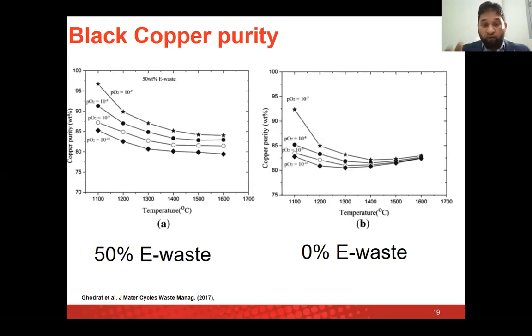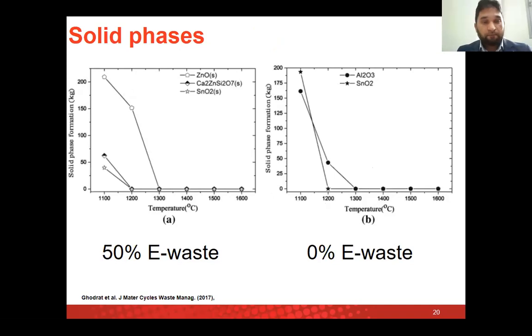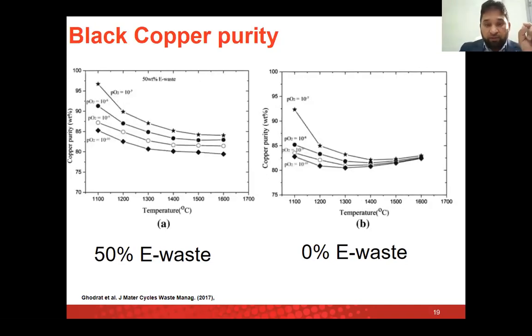So anyway, basically overall in these cases, now we will discuss, we have 50% feed electronic waste, and another case is 0% electronic waste, a simple secondary copper smelting route. Okay, so here in this diagram was the purity of the copper. And look, during the reduction process, the copper we achieve is about 80%, 85% pure. Even it can go up to higher percentage, but you need to have a higher oxygen partial pressure that we don't recommend basically, as I said, because of the loss of copper.